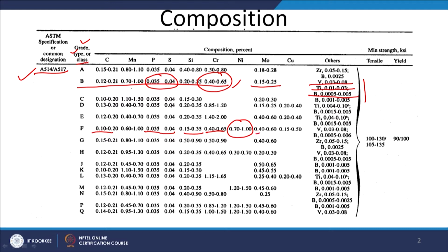and the molybdenum percentage is higher here. Earlier in the B grade it was 0.15 to 0.25 and here it is 0.4 to 0.6, and likewise the concentration of the other elements. So, there is an additional percentage of nickel and molybdenum. These elements in the F grade are extra as compared to those present in the B grade steel. So, the extra and additional percentage of the elements in F grade will lead to the higher carbon equivalent.